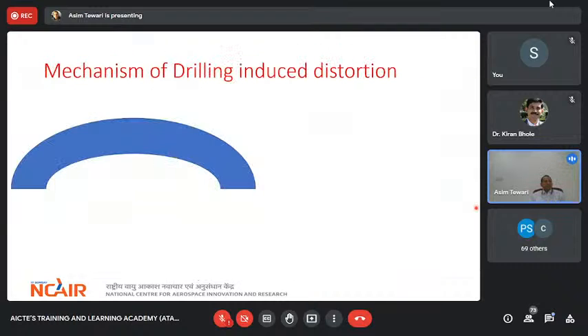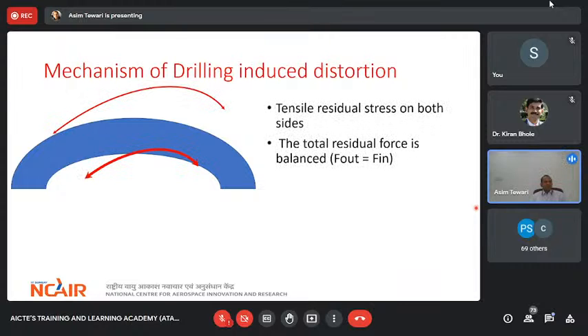So if you think about drilling, what you realize is that you basically have tensile residual stresses and compressive residual stresses. And both are essentially, in this case, tensile. So you have tensile residual stresses outside and tensile residual stresses inside. This is slightly distorted for some reason, but anyway, you understand the point. So this has tensile residual stresses both outside and inside.